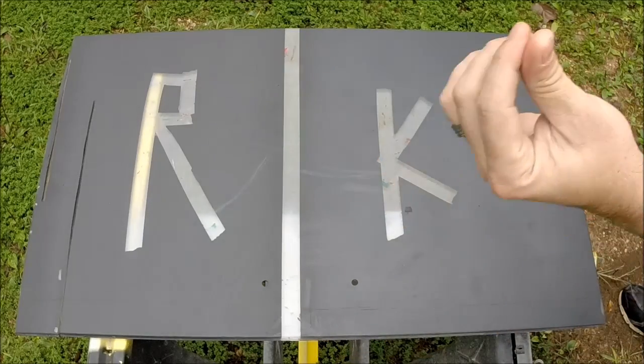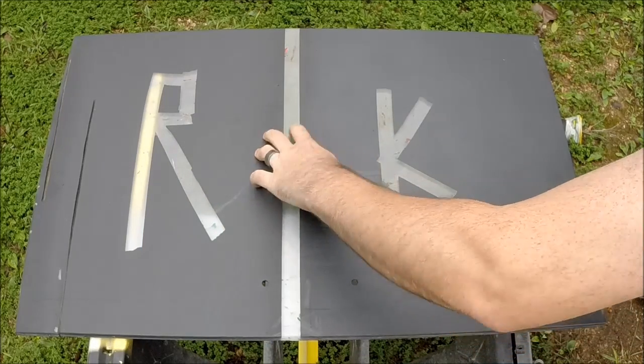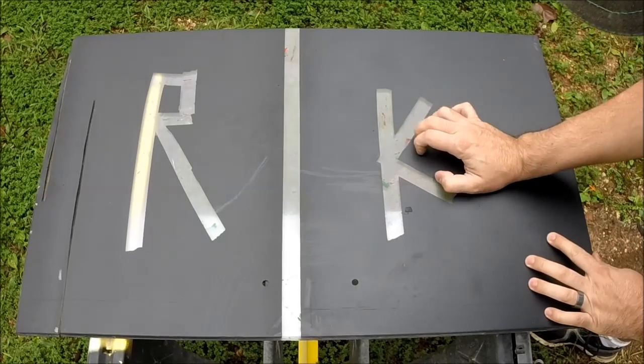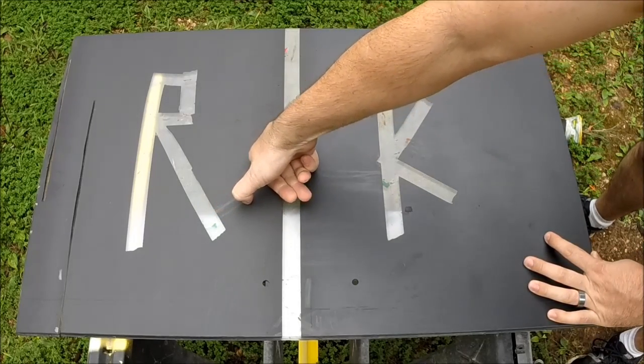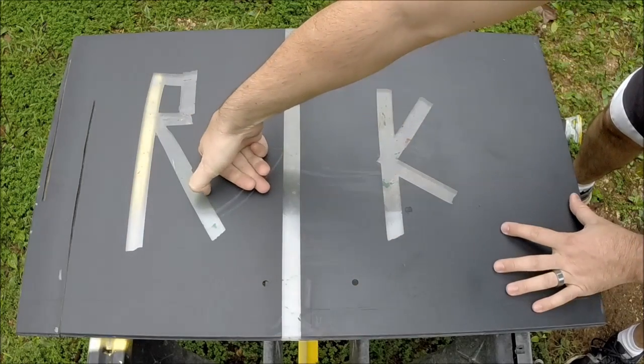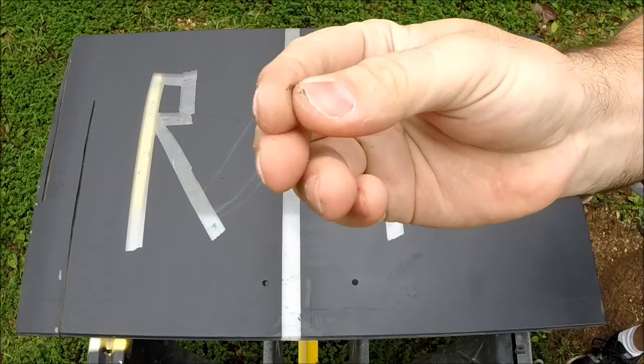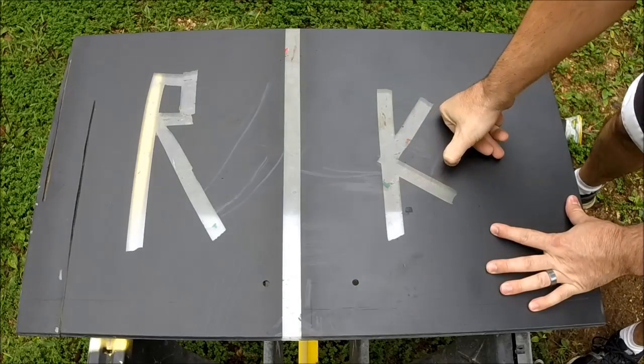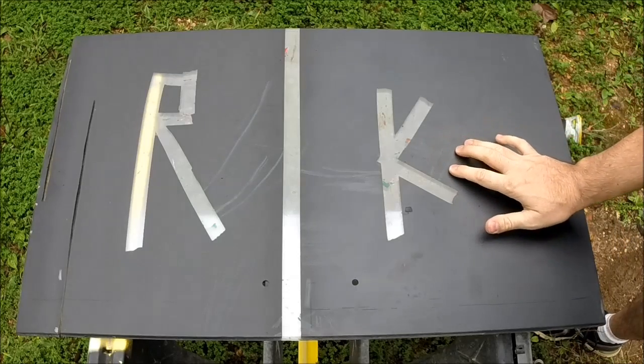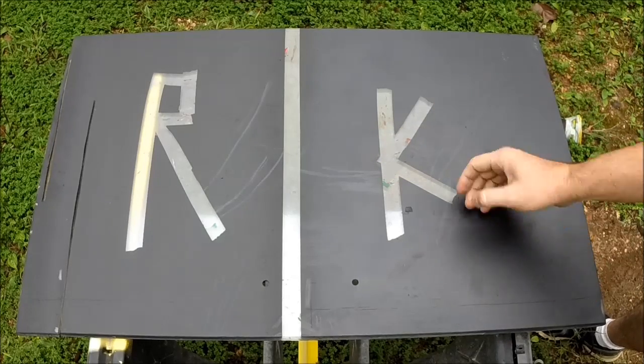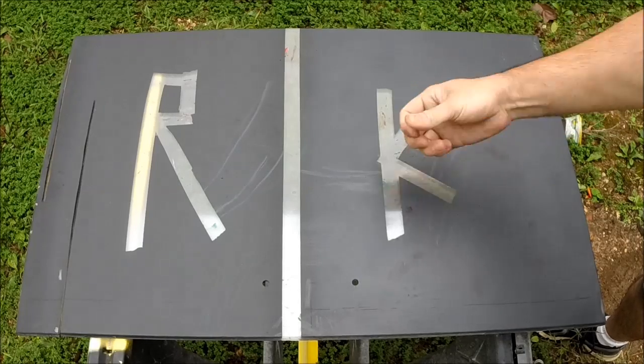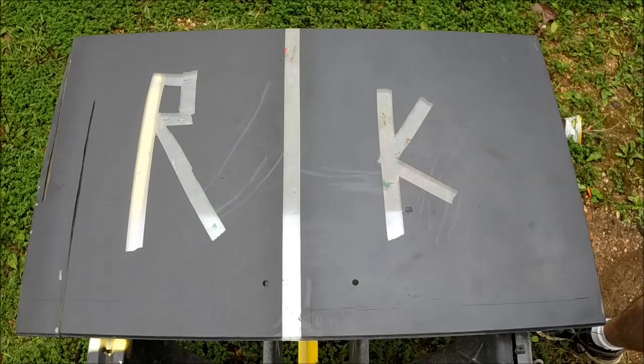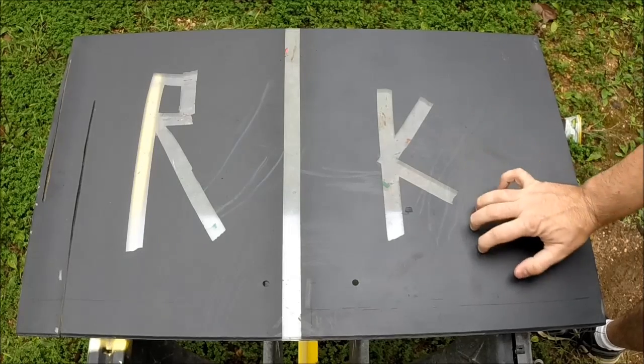There's a little bit coming off, but not much. Just off the surface. The Krylon is actually bonded to the polycarbonate. I can't remove it as a whole like I can the Rust-Oleum. When I do that, I can't feel my scratch marks. It looks like the matte finish of the Krylon is just being polished by my fingernail. I can't really remove any of the material.